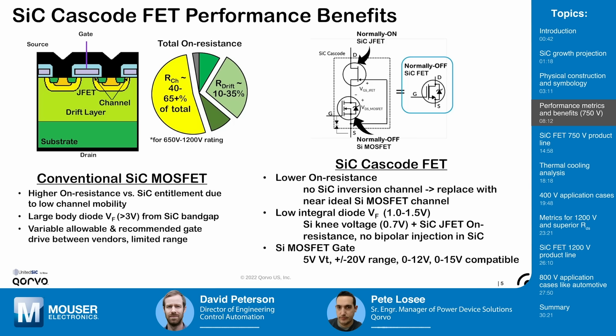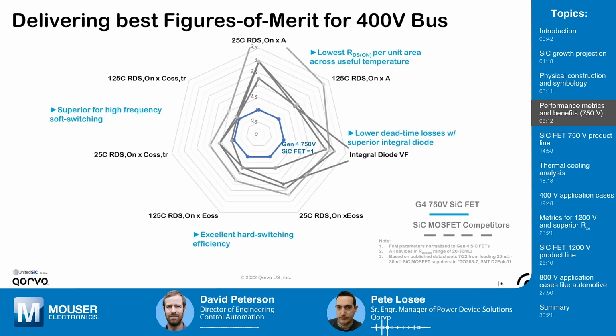So if I just sum up all the benefits that come from the lower RDS on per unit area, I can define a set of figures of merit for, let's say, a 400 volt bus where I consider either 650 or 750 volt devices. And I can plot this radar chart of all of the key parameters that one might consider for hard switching or soft switching circuits. In this case, what I did was I normalized the Gen 4 silicon carbide FET, the 750 volt FET, to the unit value of 1. And so you can see quickly that the octagon of blue is the lowest radius, so smaller is better here. And so there's not really a compromise on any of these key parameters, right? So that's the first thing you notice.